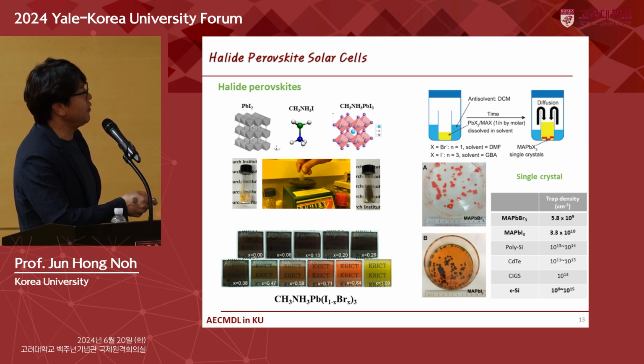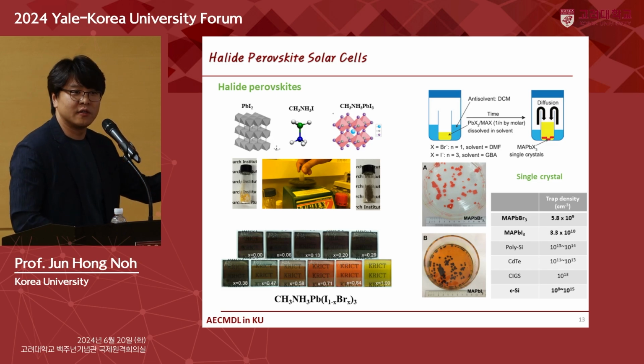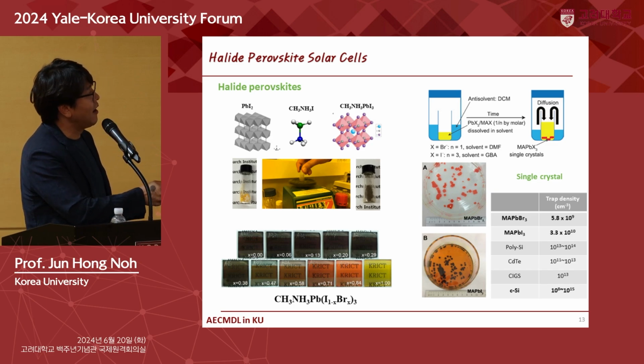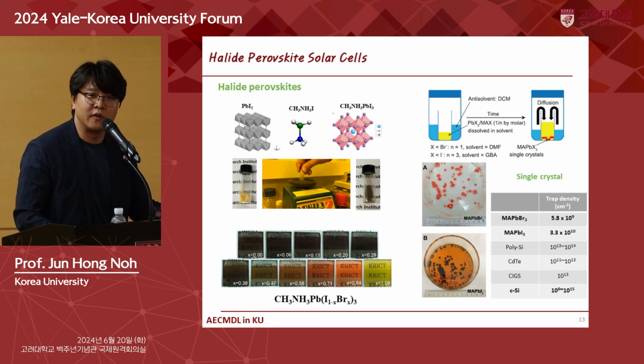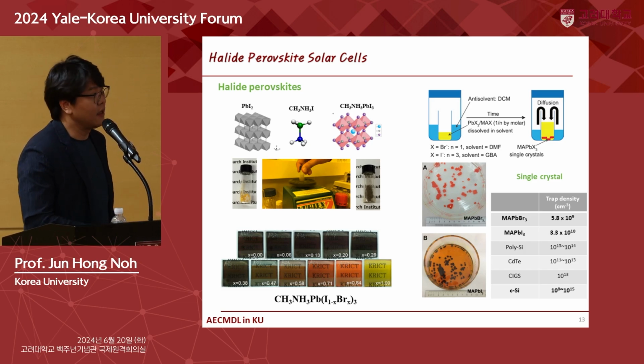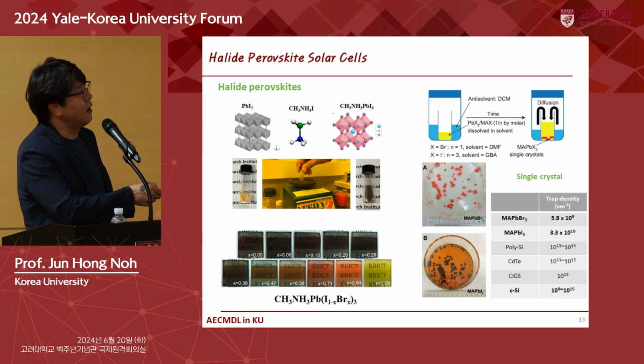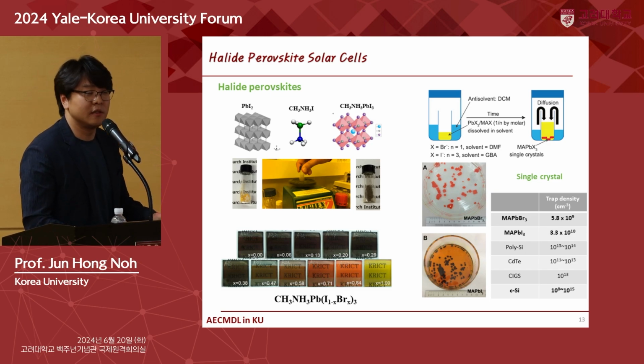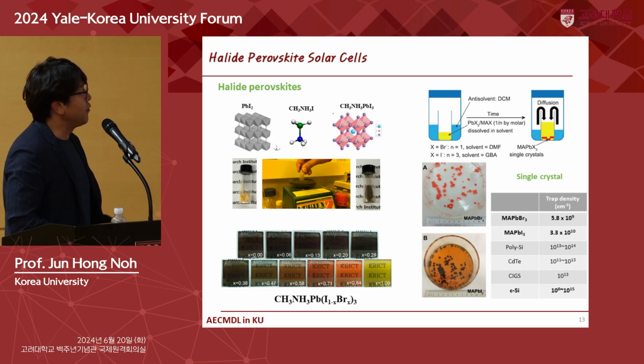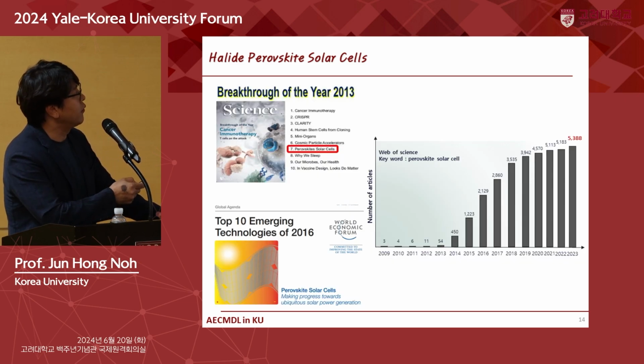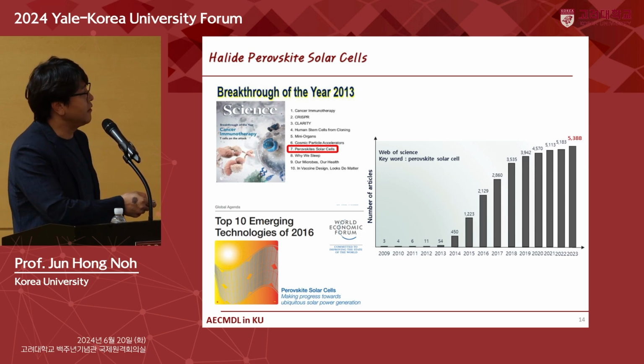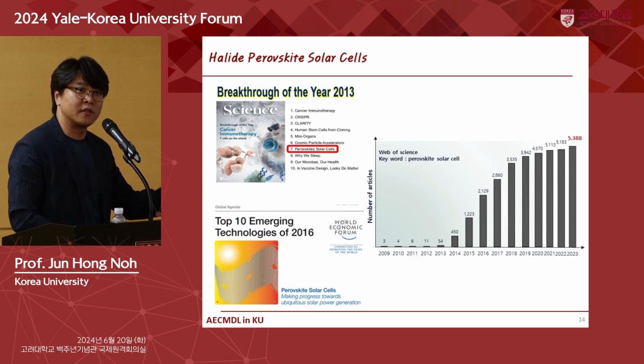I will just show you how easy it is to make crystalline perovskite materials. You just mix lead iodide powder and methylammonium iodide powder, and then you can obtain black powder at room temperature. You can also obtain single crystal perovskite materials at room temperature using a solution process. And this crystal is comparable to crystalline silicon. As you can see here, this material has a very low trap density, comparable to silicon. Perovskite solar cells were selected as one of the top 10 breakthroughs in science and by the World Economic Forum, and at this time about 5,000 papers related to perovskite solar cells are reported annually.